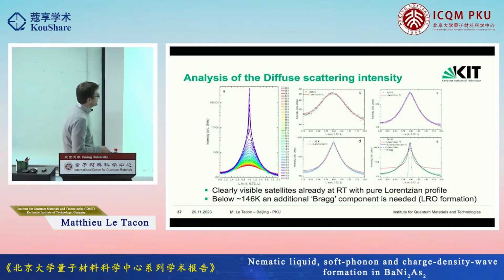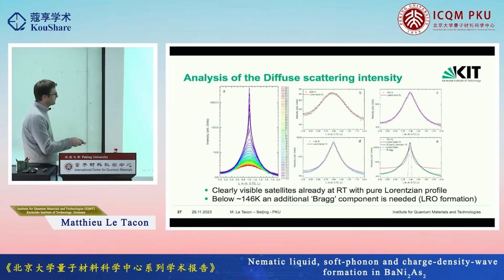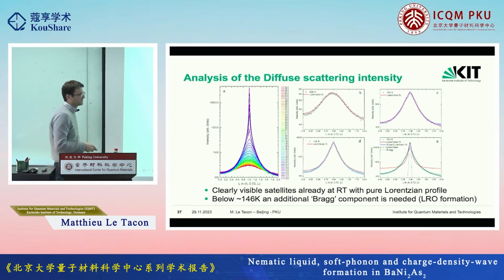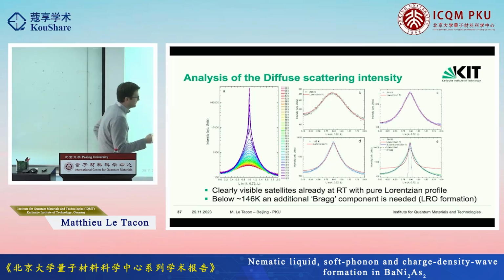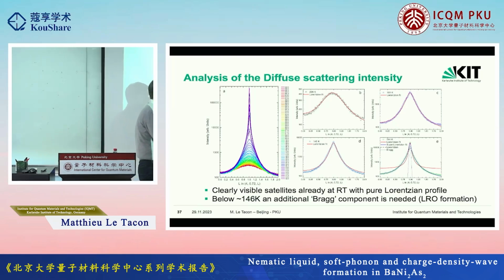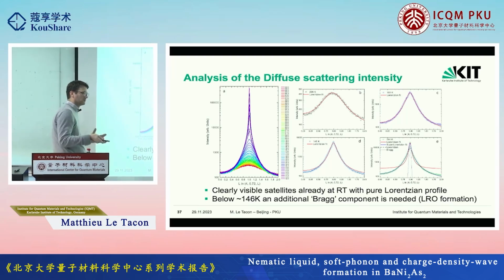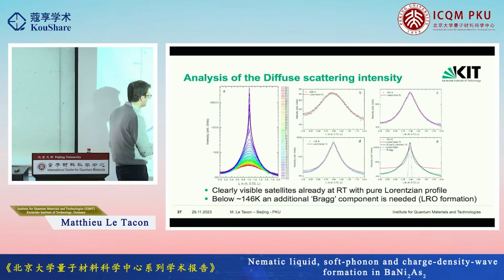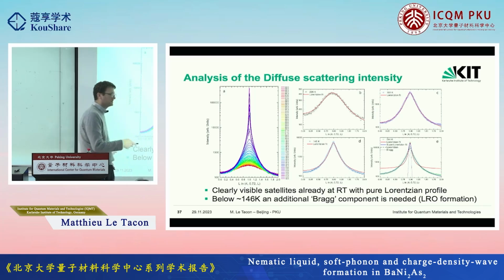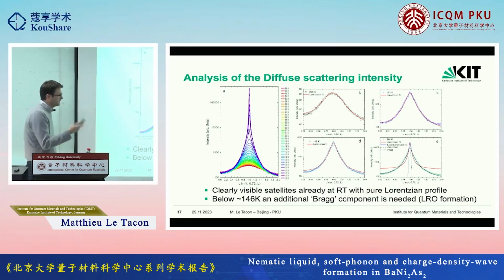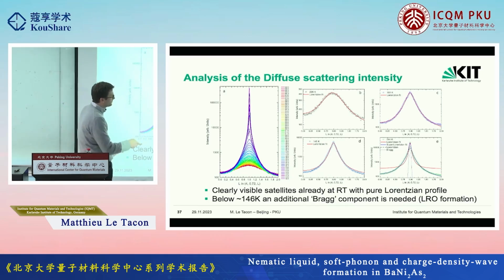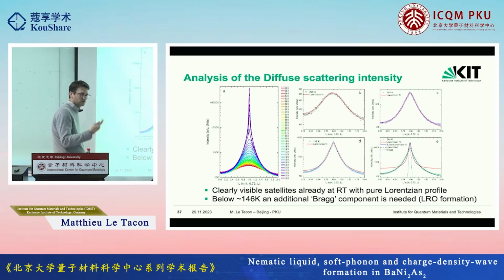We can also analyze the line shape of this diffuse scattering, and it's quite interesting. So if we look along the L direction, what you have at high temperature is a strong diffuse background, which can be nicely fitted by a Lorentzian function. And as you can see, as you cool down, the peaks get sharper and sharper, and actually, at some point, you cannot fit this with a Lorentzian background, and you have to use the so-called super Lorentzian profile. And this super Lorentzian profile, in a nutshell, tells us that we still have this diffuse background, on top of which we have a real resolution-limited Bragg reflection. Okay, so this is a criterion from which we can see when we still have the fluctuations and when the order appears. In a nutshell, when you cannot fit your fluctuation profile with a simple Lorentzian, it means that you have a real Bragg reflection and you have long-range order.